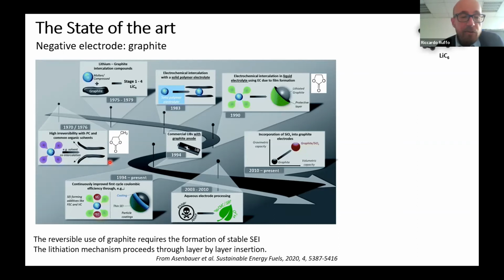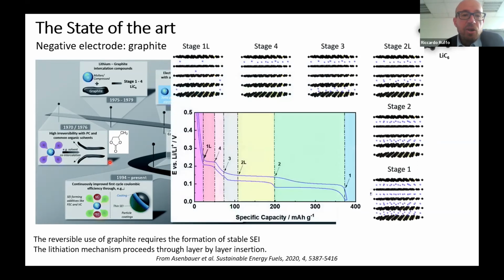a very failure result. So the intercalation of lithium into the graphite is made with several steps, where the lithium is filling the different layers that you have into the graphite, and we can go up to 370 milliampere hour per gram, which is a remarkable value, with several stages. And you can see that the potential is very close to that of metallic lithium. So graphite is a very good anode material